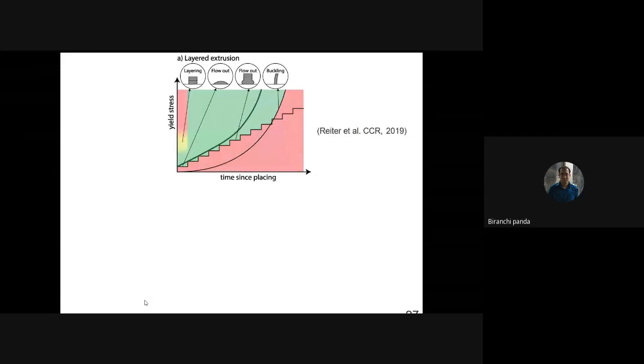FDM printing. It means that as soon as you deposit the material, it must be hardened so that you can deposit more layers. Because if you want to print 10-20 layers, you may not have to harden the material quickly, but if you are targeting to print a 2 or 3 meter tall structure, we have to find some mechanism so that this complete printing system can be made in such a way that once you deposit the material, it will quickly harden, and then you can deposit more layers.